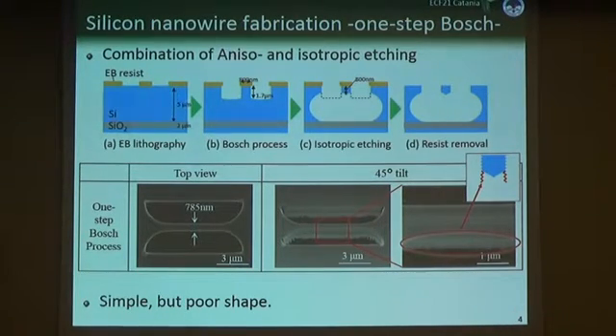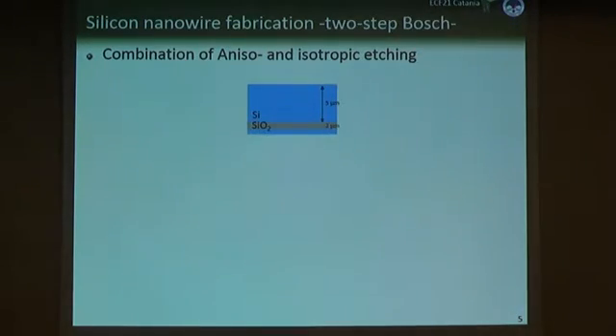So in order to control the thickness more precisely, we developed the second method. We call it the two-step Bosch process. Again, this is a combination of anisotropic etching and isotropic etching. First, we put on the EB resist for the mask, and use the Bosch process and anisotropic etching with fine scallops to determine the width of the wire. Then we switch the recipe to make undercutting of the wire by changing the length of times of the etching and the passivation process. So the wire is undercut.